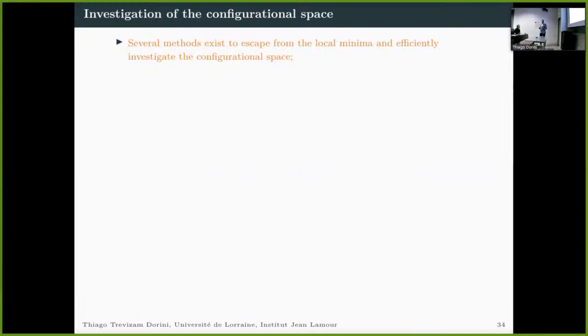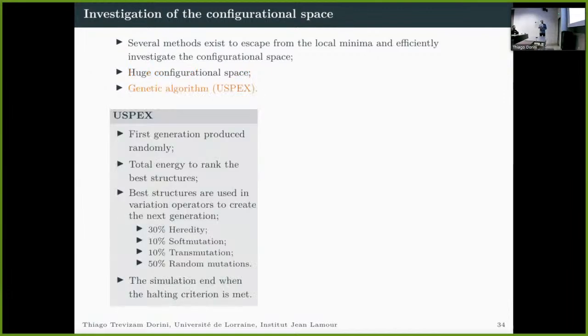In this case, we need to search a very big configurational space, and there are several methodologies we can use to do this. There are Monte Carlo simulations and molecular dynamics, and in our case, since we have a huge configurational space because we change the substrate size and also the oxide composition, we chose to use a genetic algorithm with the USPEX code. Here we have a small recipe of how we did these calculations.